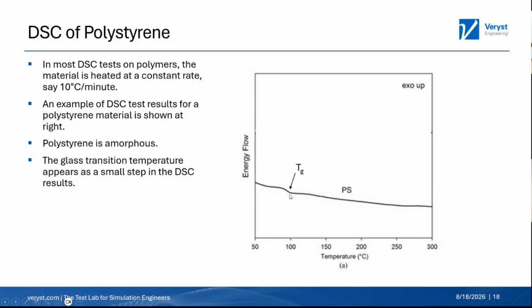It's pretty common for a lot of amorphous materials when you're trying to measure the glass transition temperature with DSC. So this is the kind of technique where it does take a little bit more experience, something of a trained eye, to actually pick out what's Tg and what's just noise. But this is how you measure that for a fully amorphous material.